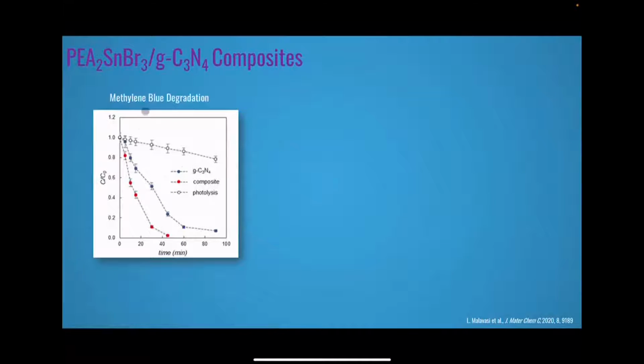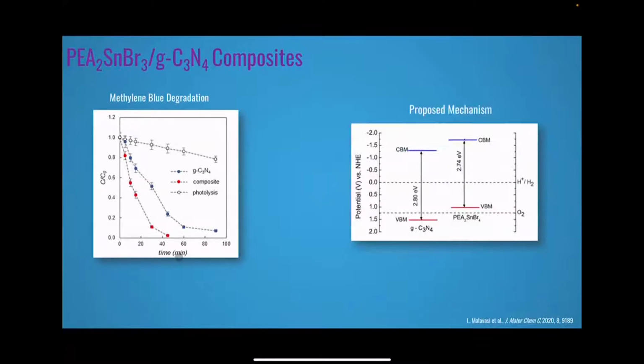And we also tested these composites against organic dye degradation. Here you see, for example, the composite and the pure graphitic carbon nitride. So the composite, the heterostructure, works better. And again, we also thought about the mechanism.